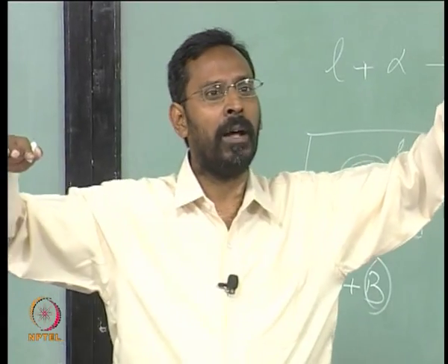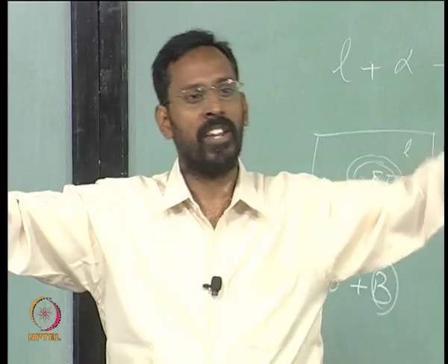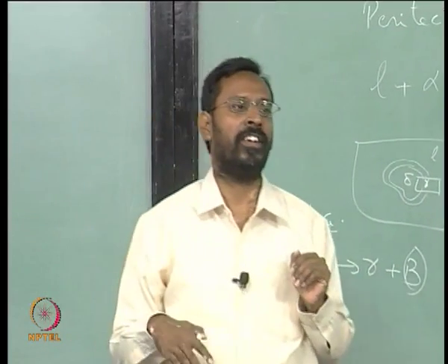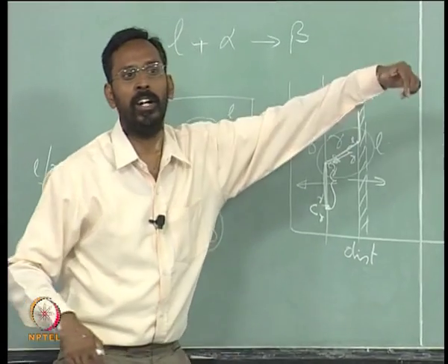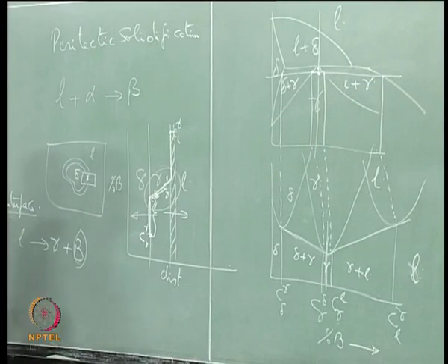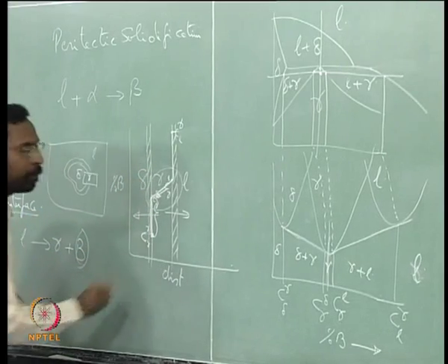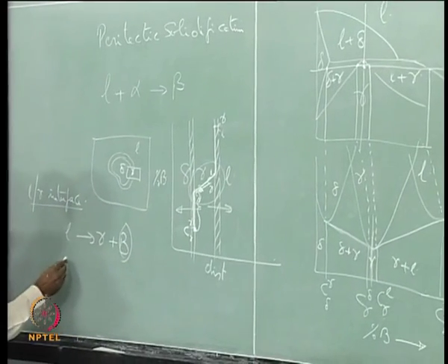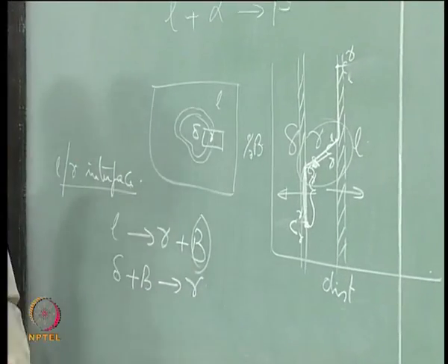The composition of the delta becomes equal to the composition of the gamma, and once the compositions reach the same, suddenly there will be a BCC to FCC transformation, and that means a small amount of delta got converted into gamma, and as a result you will see a small volume here gets converted. And what is the process? The delta takes B atoms and gets converted to gamma.